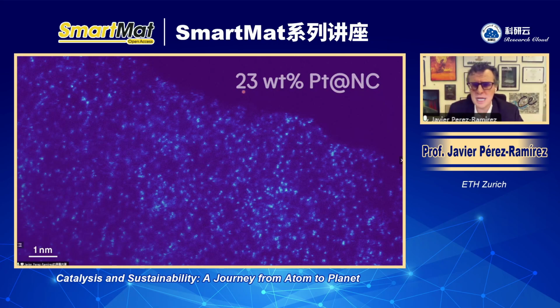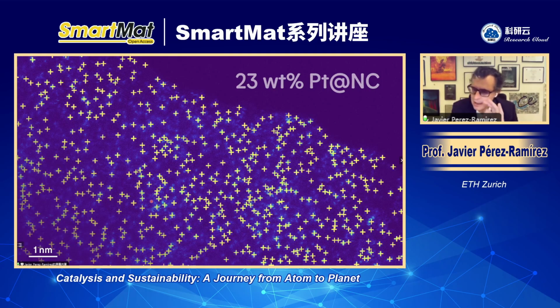Now, I told you before about ultra high density single atoms. So this is a 23% weight platinum on nitrogen doped carbon. And you can see here the bright spots in the microscopy image, right? Now, the algorithm nowadays, in less than a second, will position, according to the understanding of the algorithm, where the single atoms are located, what's the distribution, and so on. You can see that here by yellow crosses.